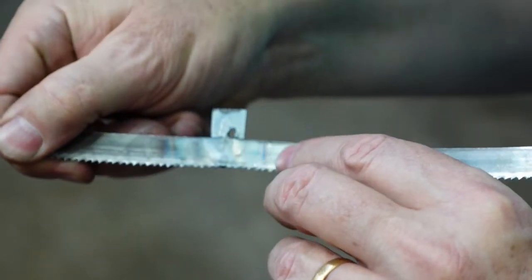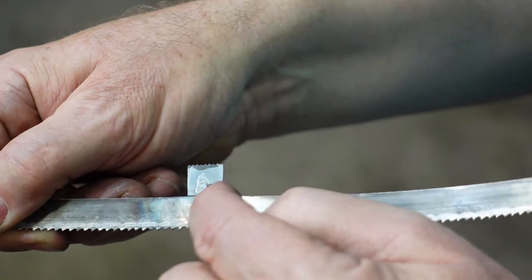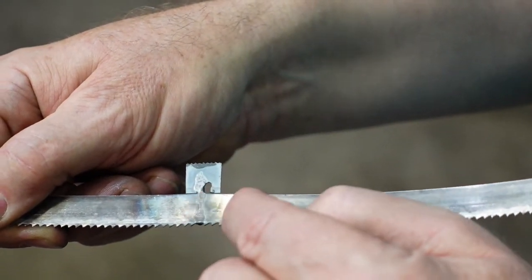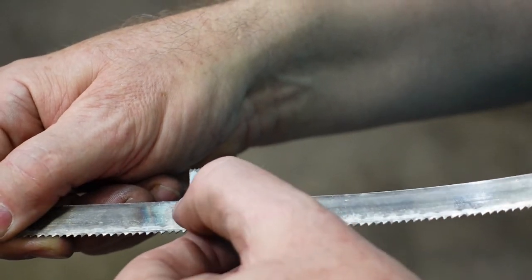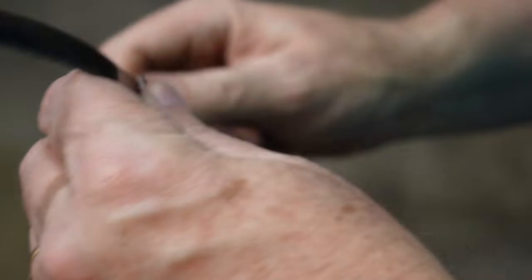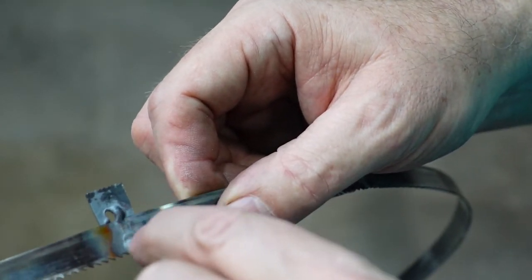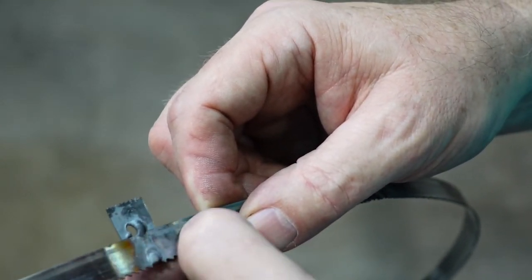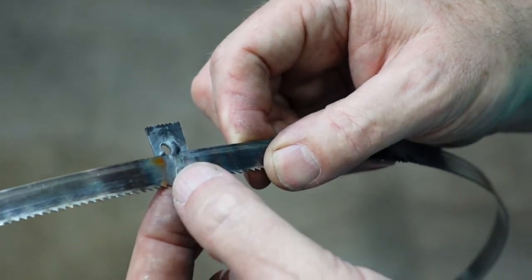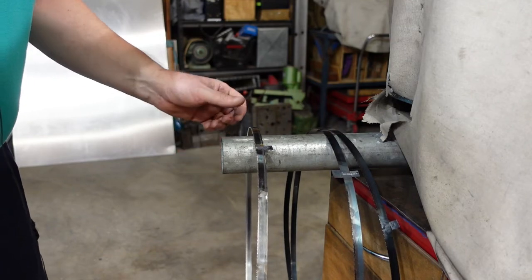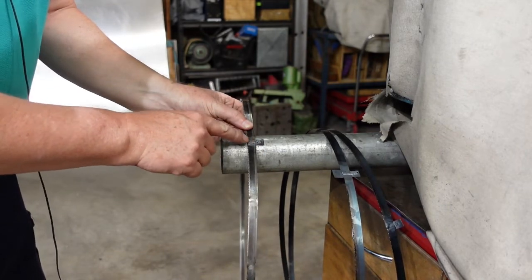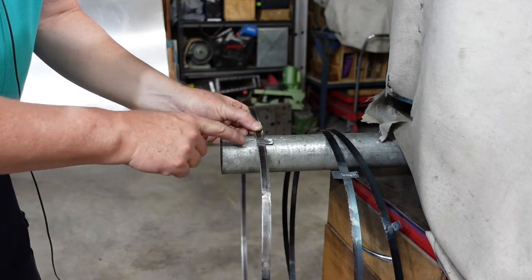If I flip that round, hopefully you can see the back of that. There's very little weld build-up on there. I've got full penetration, but there's very little weld build-up on there, so that's a good thing. What I have to do now is basically cut off these tabs, and then using an angle grinder or a linisher or a bench grinder or whatever I've got, get that down. What you're trying to do is grind that so that it's basically the same thickness as the blade, which is why you want the good penetration. To grind these, I've got a piece of water pipe and I use that basically as a support. So I'll come along and I'll slice those off, but when I'm grinding this I'll have that back against the pipe so that it just gives me a surface to work against.